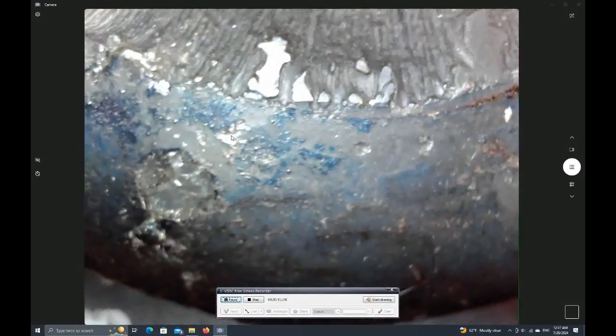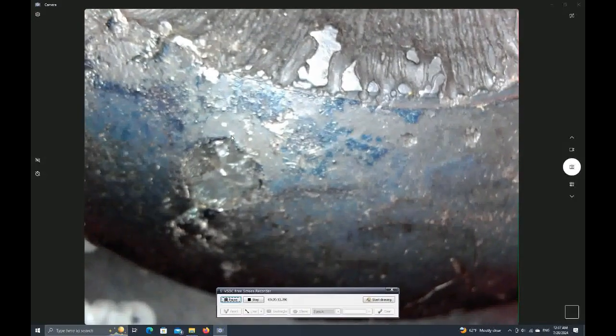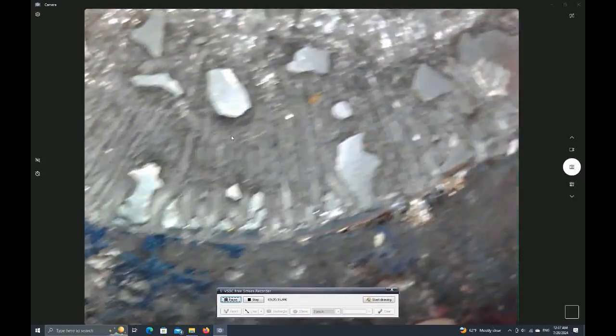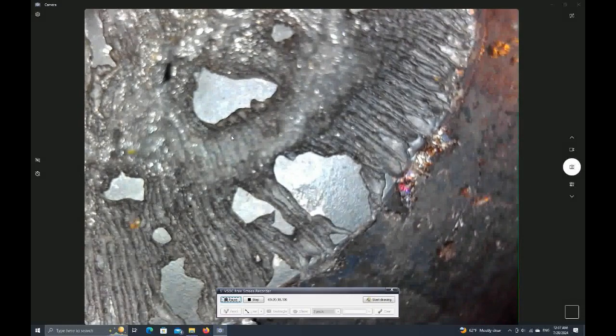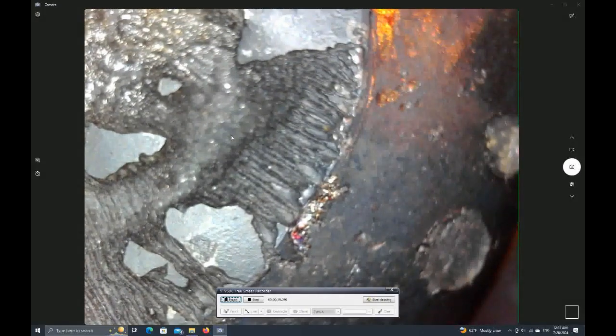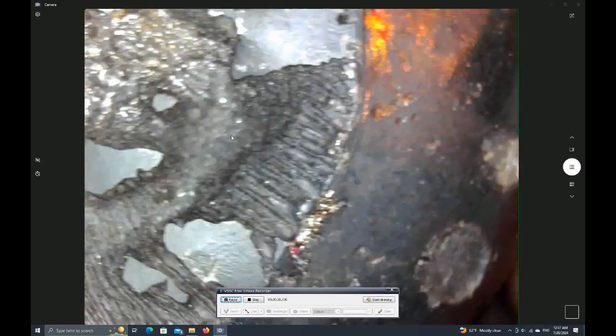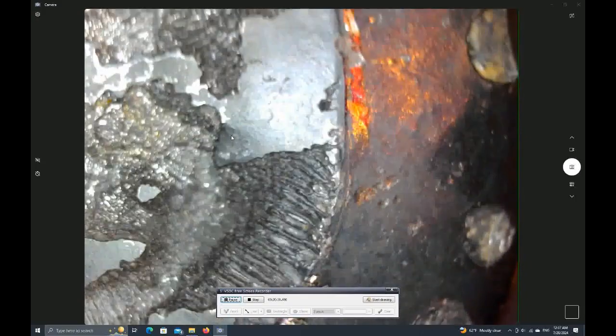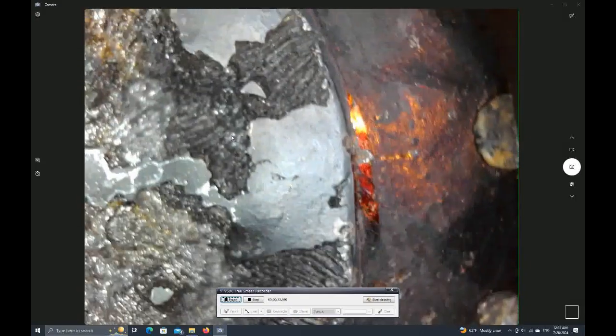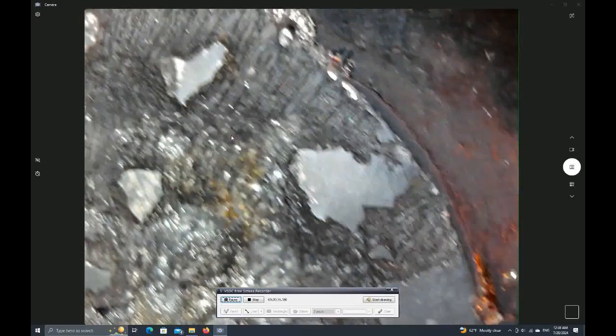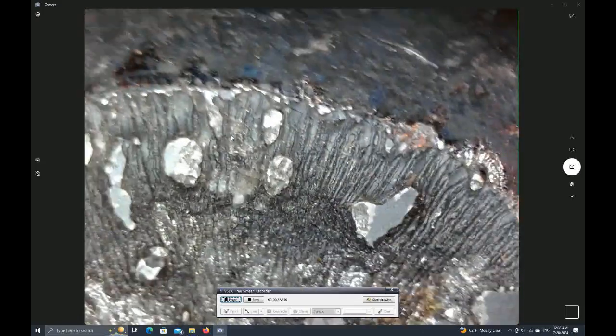Check out the gorgeous colors here. Again, that is oxide formation. Basically, the ingot was completely covered in glass and so protected from oxygen in the periphery, not obviously in the middle. But I chipped away the glass when it was at elevated temperatures such that it formed those iron oxides that then scatter light and appear as colors.